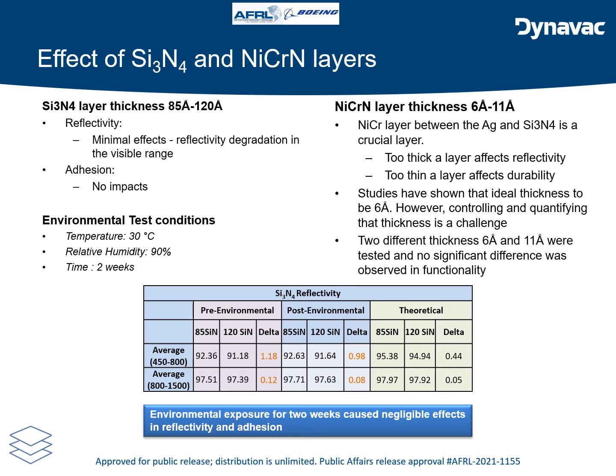Fortunately, we did not see any difference in the optical properties and the adhesion properties, which is good news. So, there is a range of thickness we could live with, and it will not show up any adverse effects on the reflectance and the adhesion properties.